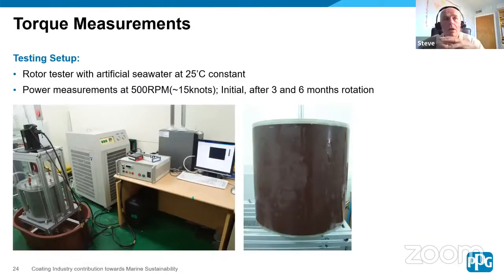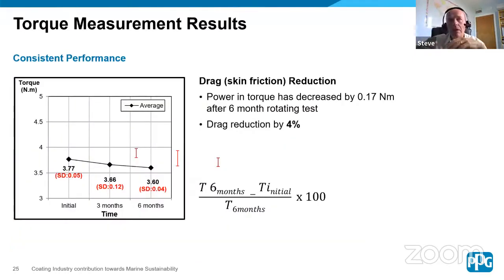Pusan University in Korea, different type of measurement, looking at torque as an indicator of resistance, an interesting way of measuring frictional drag, measured initially and then over 3 and 6 months. And what you see is that deterioration, that drag reduction, which will already be low because of that very, very smooth surface that we saw in the laser microscopic photograph, improves further again over a six-month period by 4%.